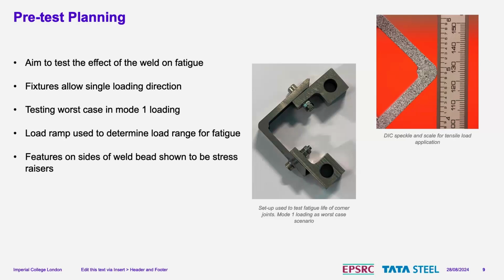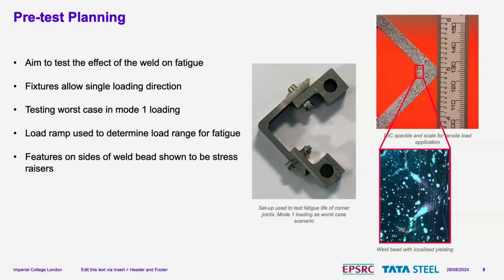My initial test was to take one of these. It does look like there's machining marks on this. There are for the actual samples. They were nicely polished and ground, so those were not detrimental to any of the tests. I then put a speckle pattern on it, did some more DIC, and just loaded it from 0 to 10 kilonewtons. At the end of that, you can just about see this is our weld bead that we saw before, and these are those two features. And so we do get some localized yielding around those features, which just confirms that these might be an issue when it comes to fatigue.